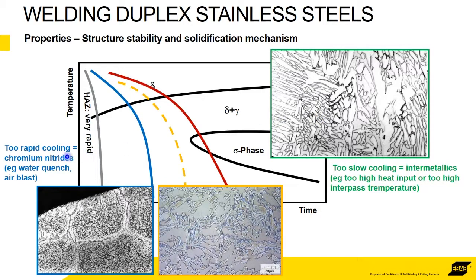Similarly, again, the welder wants to go home. He wants to get another pass in, another couple of passes in. He doesn't want to go over on the interpass temperature, so he quenches with water, say, or air blasts. If you're cooling too rapidly, then you get massive grain structure and chromium nitrides, which is equally as bad. What we're trying to achieve is a nice middle of the road and maintaining this nice duplex structure.